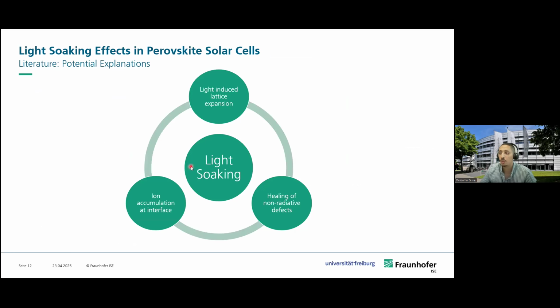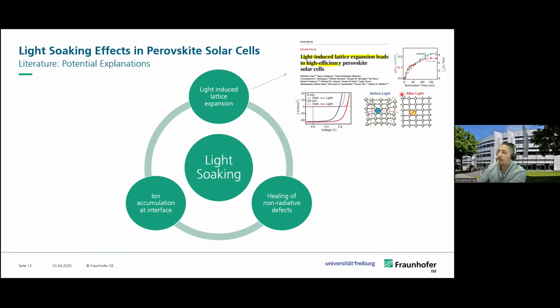And there were 3 main reasons. The first one was light-induced lattice expansion, where researchers have found that there was a direct relationship between the VOC and fill factor change during the illumination time and the lattice parameter, where during illumination, the lattice parameter would increase, then inducing a light-soaking effect.